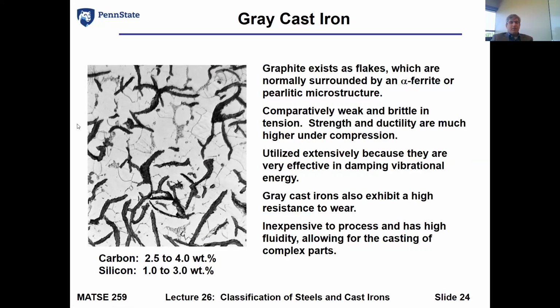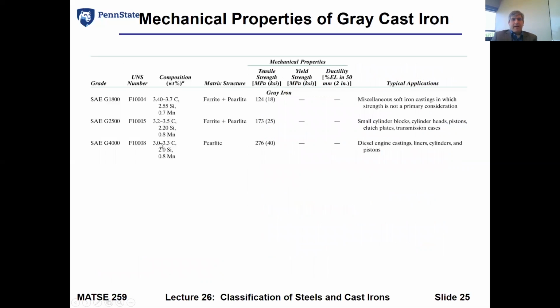But let's look at what the microstructure looks like. The gray cast irons are primarily defined by these flakes of graphite. And so you can start thinking about why they would be weak and brittle in tension. Well, you look at the ends of these flakes. They are very much stress risers. And so these stress risers will tend to limit that ductility and that strength in tension, because we already have a lot of high strain, high stress areas locally within the gray cast iron. Mechanical properties are good. You want to use them in castings.